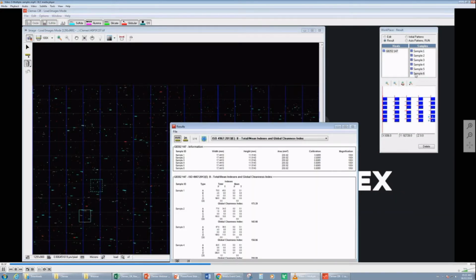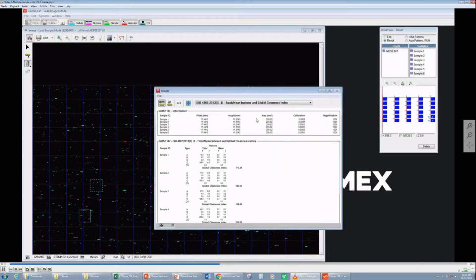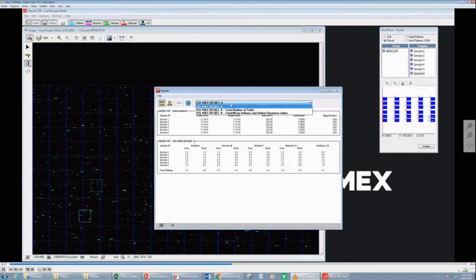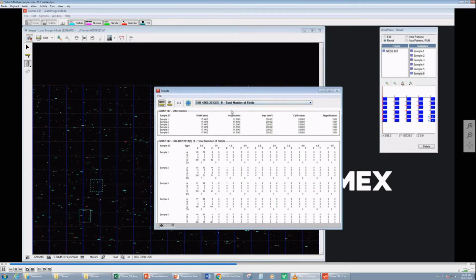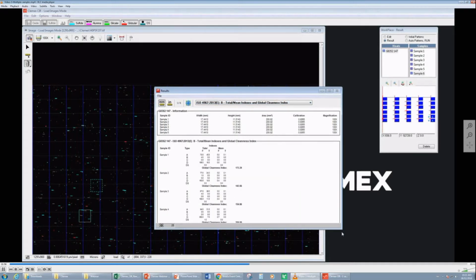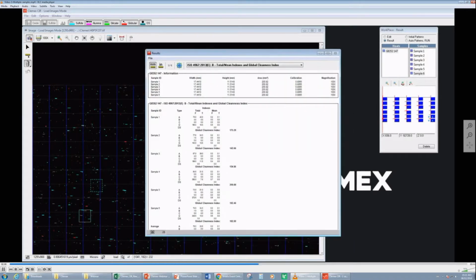So here we have the results for all of our samples. As you can see in this window, we have the different methods for the ISO standard. We have method A, B for total number of fields, and also B for global cleanliness index. So we get the average per sample and also the average for the whole heat on the bottom.